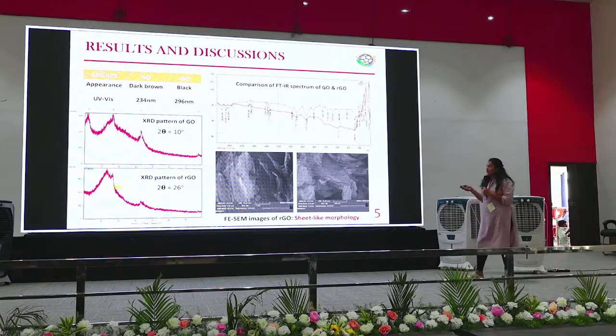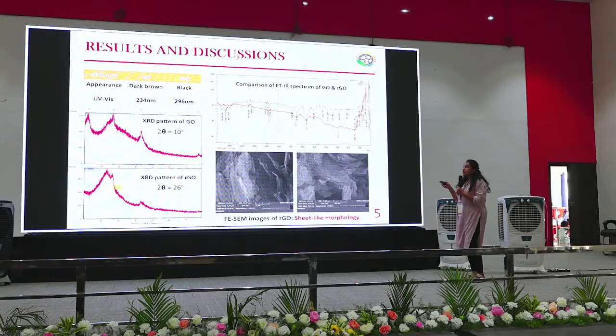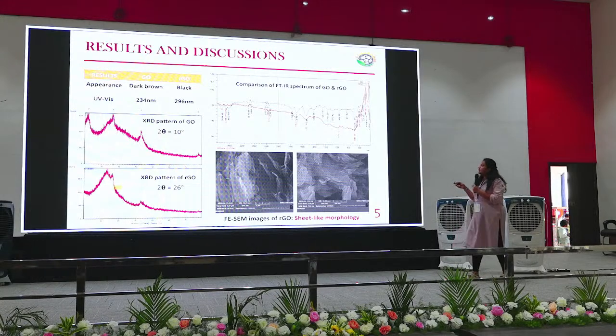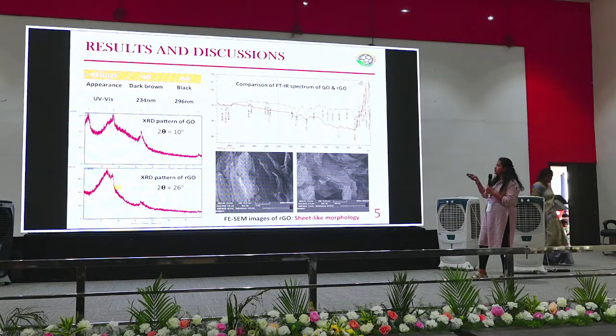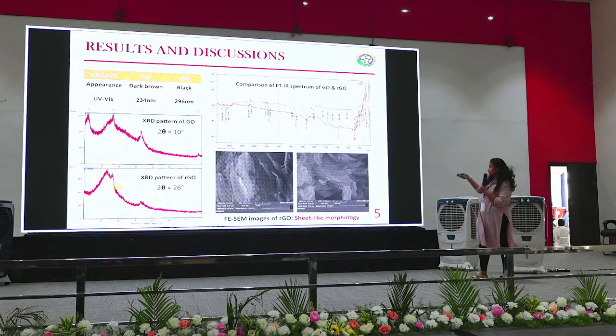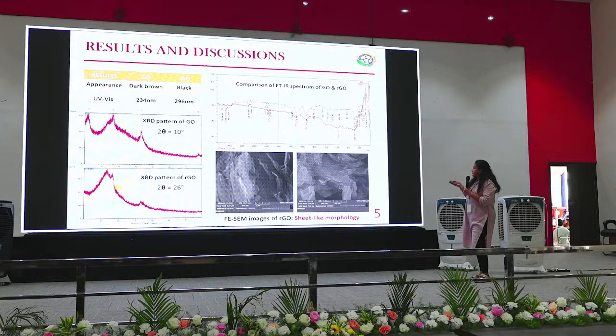So this RGO is characterized by UV, where the dark brown color solution of graphene oxide changed to a black color solution, which shows spectra of 234 nanometers to 296. The comparison of FTIR spectra shows the effective reduction of graphene oxide. There you can see that the oxygen functional groups are being reduced, and some even disappeared.